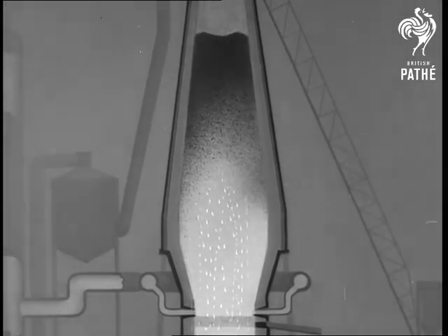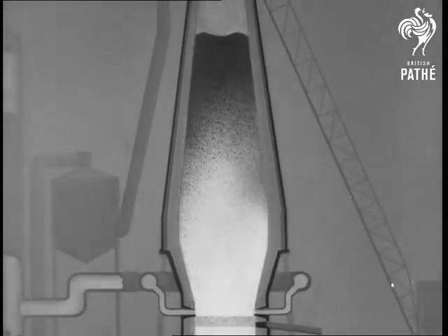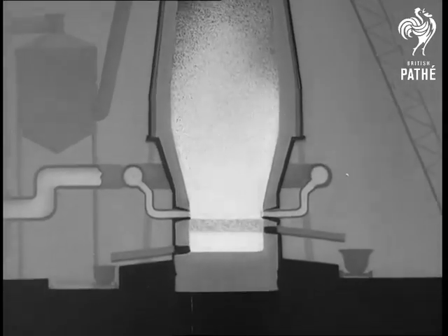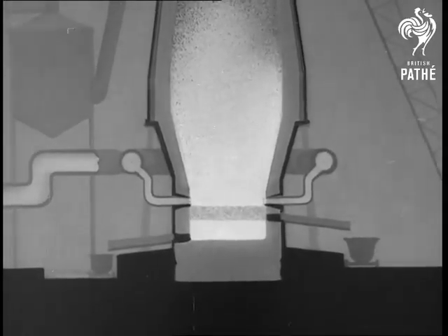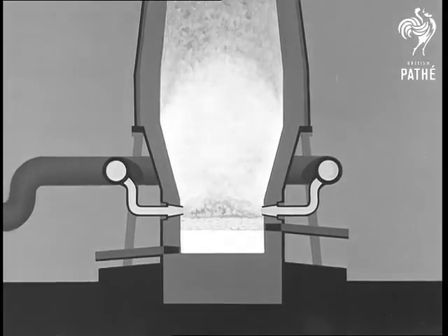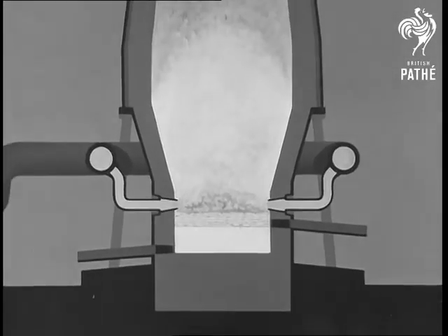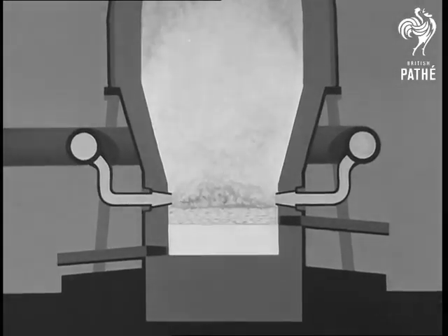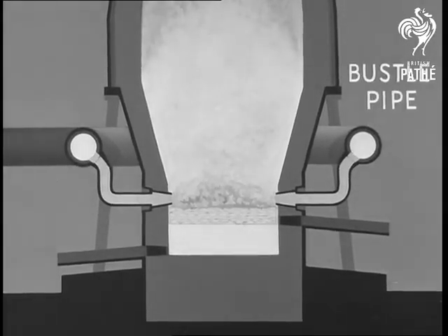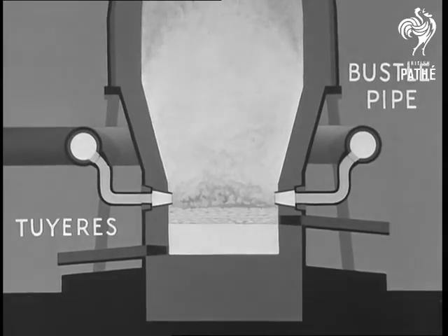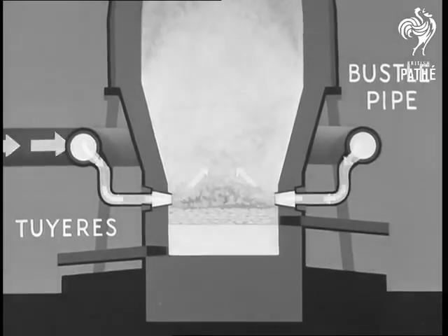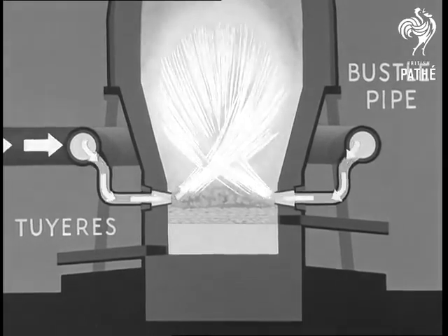A large furnace can produce 1,000 tons of iron per day. To do this, it needs some 2,000 to 4,000 tons of ore, 800 tons of coke, 400 tons of limestone, and 4,000 tons of air. This vast quantity of air travels at great speed round the bustle pipe and into the furnace via the tuyeres. The speed of the preheated air leaving the tuyeres may be as high as 6 to 7 miles per minute.